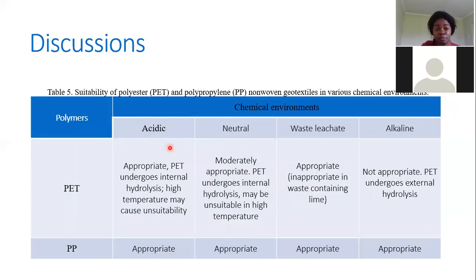So on the suitability of polypropylene, someone might ask, which one should you use? We found out that polypropylene can be used in all environments. However, internal hydrolysis takes place, and over a long time, this might cause some unsuitability. While polyester should not be used in alkaline environment, because external hydrolysis takes place, and external hydrolysis is more severe, it's more dangerous than internal hydrolysis. On the other hand, polypropylene can be used in all chemical environments, irrespective of the pH value.